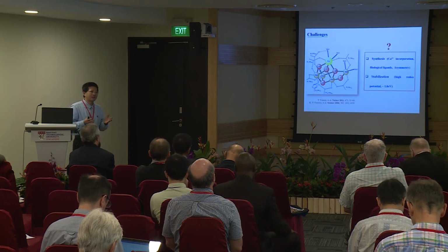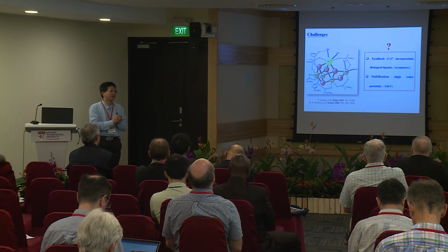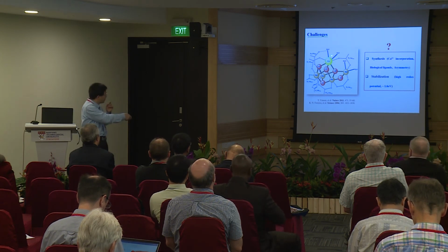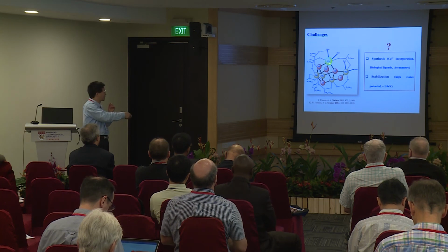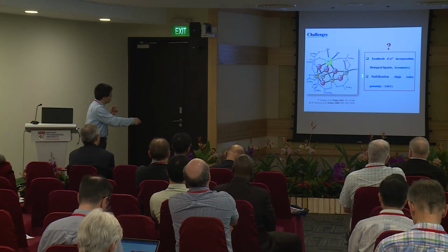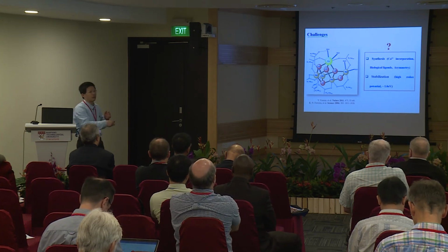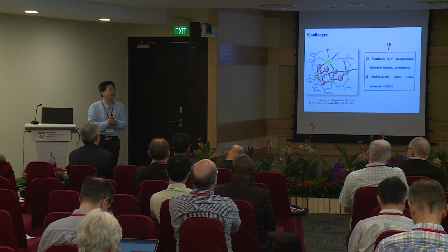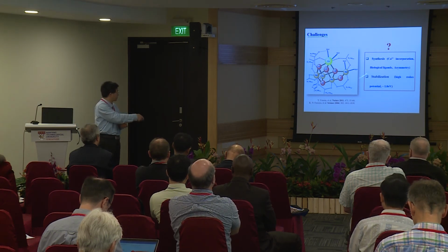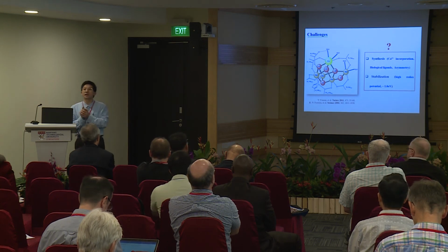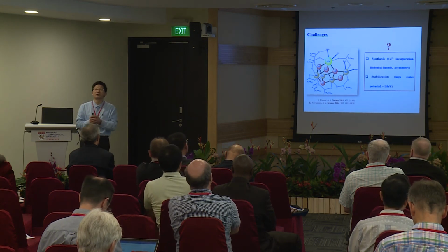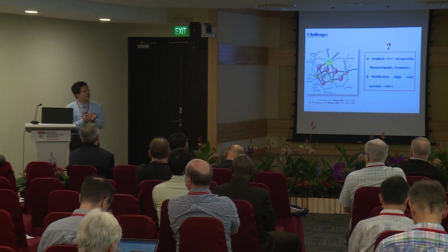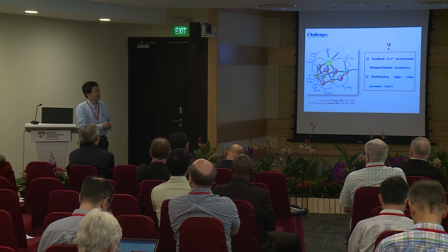But it turned out immediately that it's really hard. Why? Because it's hard to put calcium in like this. It's also very hard to mimic the biological environment and put water here, and the structure is asymmetric. Another problem is that the redox potential of the OEC is very high, close to 1 volt, and nobody knows how to stabilize this in solvent.